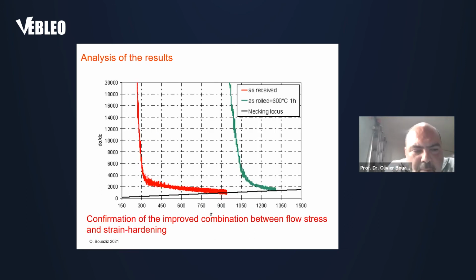So let's go back to the Kocks-Mecking plot. So the strain hardening is a function of flow stress. You see in green that for a given flow stress, the strain hardening is much higher than in the as-received condition. So it is the confirmation of improved combination between flow stress and strain hardening.